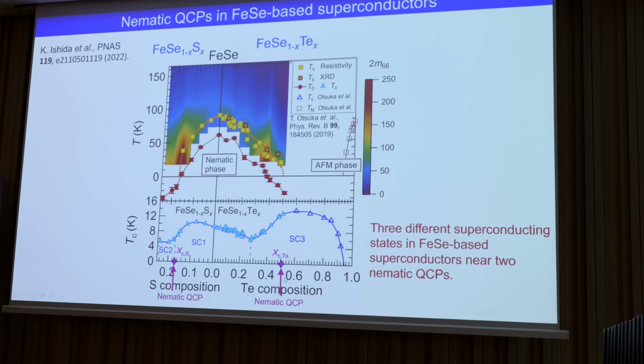What is interesting here is that we have a very large enhancement of the so-called nematic fluctuations, which can be measured from elastoresistivity measurements. In this phase diagram, we found that we have a pure nematic quantum critical point without any magnetism here on the sulfur side, and here also on the tellurium side. So in this phase diagram, we have two pure nematic QCPs without having any magnetism.